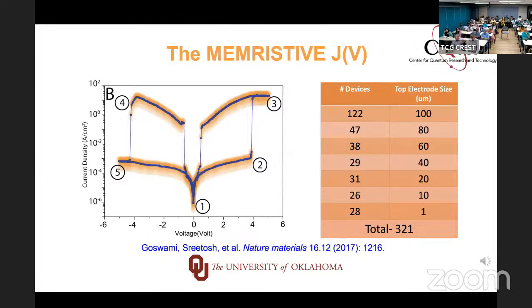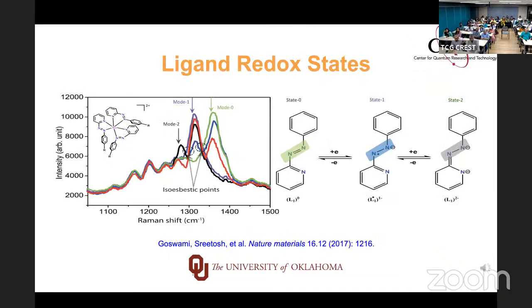So there's a J versus voltage plot, and you can see 321 devices have been looked at, with sizes from 1 micron to 100 microns. All these devices are plotted on this curve. So this is the data of 321 devices. And you can see the on and off are very cleanly separated, which means these are very highly reproducible systems. Now, the system exhibits a lot of amazing things.